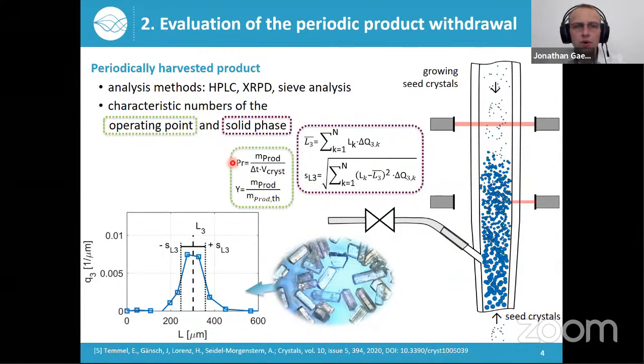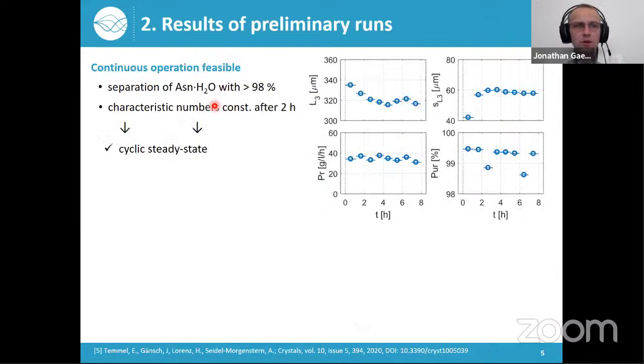And using these 4 characteristic numbers, we could already prove the feasibility of the continuous operation in preliminary runs. Here you can see the mean product crystal size, the standard deviation, the productivity, and the product purity over the process time. And what we could observe is first that we have a successful resolution of our asparagine. All these product purities are over 98%. And all these numbers become constant after more or less 2 hours of process time. So we could prove that this process reaches a cyclic steady state, even with this periodic product withdrawal.